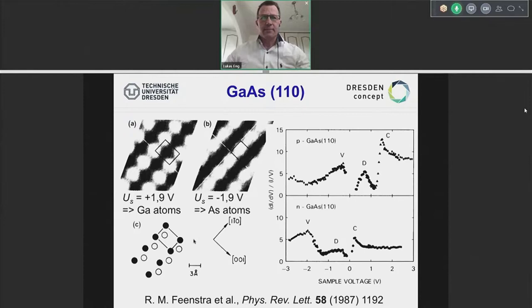Feenstra and colleagues repeated the same experiment with p-doping and with n-doping, and you can now see that the conduction band, C, and valence band totally shift from positive voltages to negative. Yes, this is a brilliant example to really probe individual atoms, and that's possible as long as, in that case, an electron can tunnel into these systems. That's clear. What's going on?